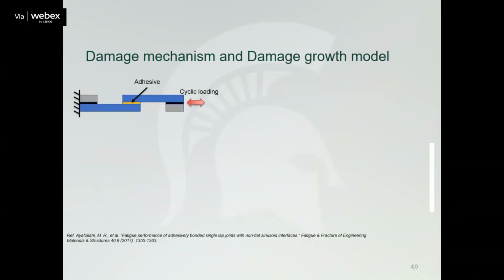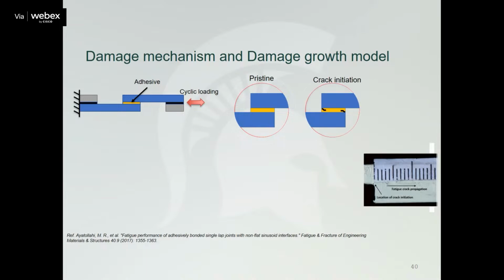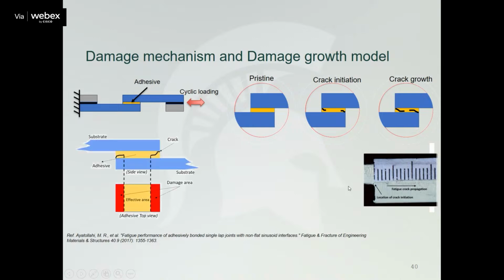Okay, so for this particular problem, when we talk about the damage mechanisms and damage growth model, we start from the pristine state. Subject to cyclic loading, then you can have a crack initiation. We always want to understand that, so we start from the optical technique. You can monitor or assess the fatigue crack propagation, and you start seeing the location of the crack initiation from the edge of this adhesive layer, then it starts growing over time. And you can also measure optically how that grows over time in space. Then it grows from both ends, then at some time it will lead to failure.